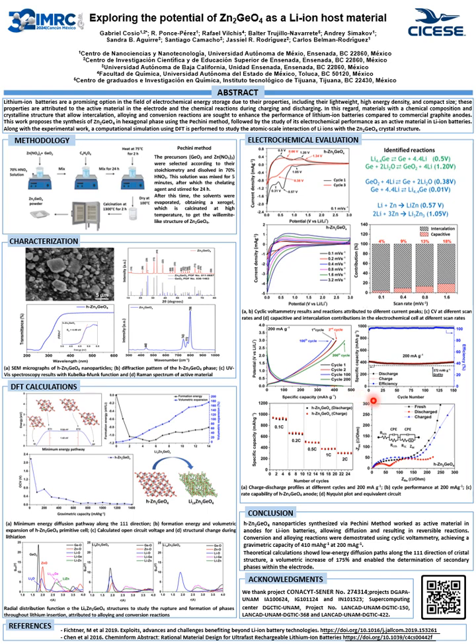The image on the right displays the electrode performance over 200 cycles, showing a trend of increased capacity beyond 80 cycles, with an efficiency of 99.9%. This image also shows capacity measured at various C rates. Furthermore, electrochemical impedance spectroscopy was performed, revealing three distinct regions in the impedance spectra that correspond to different resistances within the cell. The first region represents the electrolyte resistance, followed by the charge transfer resistance, indicated by the observed semicircle, and lastly, the straight line representing ion diffusion within the structure.